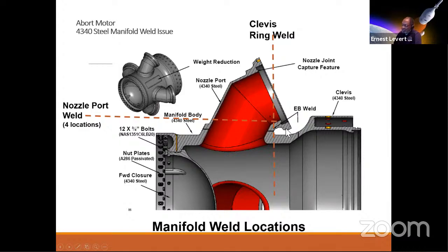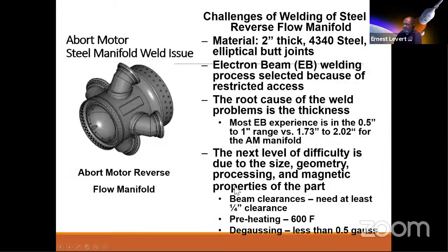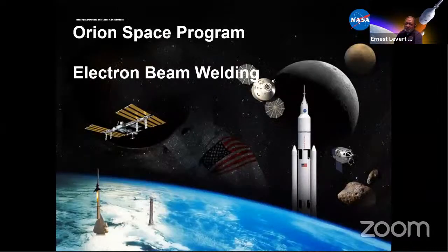And the problem you had, everyone, was magnetism. This is 4340. It was very high in magnetism. And so you had a major issue with magnetism. And with 4340, we have a preheat of 600 degrees, an interpass temperature, and post-weld heat treating. So therefore, that was a major concern we had dealing with this material. When they called me in, they had an issue with porosity and beam deflection, and they didn't know how to make this happen. So they ended up coming up with a solution.